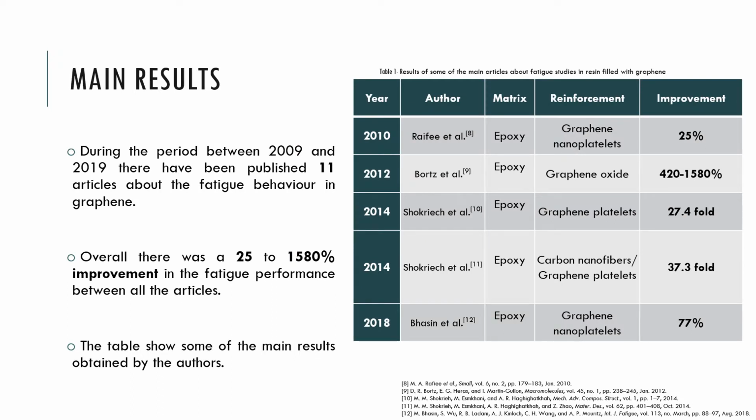During the period between 2009 and 2019, there have been a total of 11 articles published about fatigue behavior in graphene-reinforced composites. Overall, there were 25 to 1,580% improvements in the fatigue performance between all the articles. The table to the right shows the main results obtained.